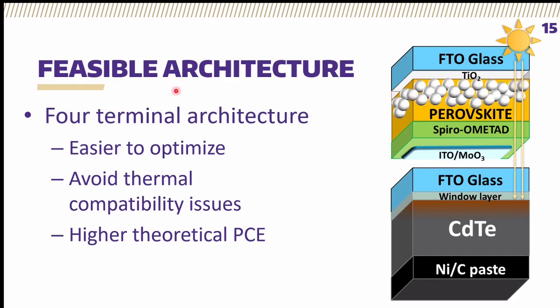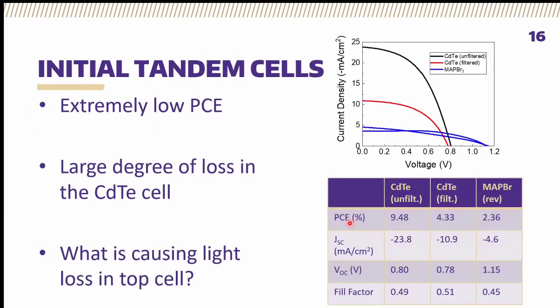Not all is lost, however. There are advantages to a 4-terminal architecture. It's easier to optimize. You avoid thermal compatibility issues, which means you can deposit TiO2 using traditional methods, and it has a higher theoretical PCE. And so what we did is we, us and our collaborators, wanted to just make a really, really suboptimal device and just see what happened. And that's exactly what we did. We made perovskite-CdTe 4-terminal tandems, and we saw they had originally very low PCE, which we attributed to the fact that we hadn't optimized our methylammonium lead bromide fabrication procedure yet.